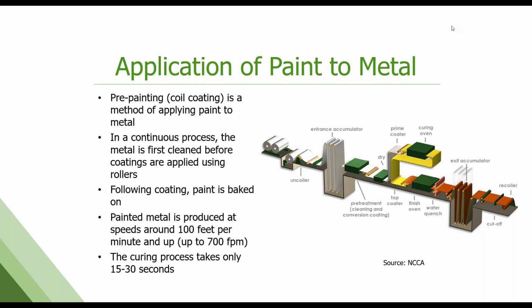It's cleaned first through a cleaning section, gets a pre-treatment put on, then a primer coat, and then a finish coat. It's baked on. Most paint lines are running anywhere from 100 to 700 feet per minute, which is quite fast. Curing of the paint, from the time it is applied to the strip to when it's cured and dried, is anywhere from 15 to 30 seconds. So very, very quick. In comparison, we always use analogies to car manufacturing, because people have a feel for that. Cars can take anywhere from 30 minutes to 2 hours to be completely coated. We can run enough coil in a matter of minutes using our process to do many, many buildings. So the scale of economy is quite large.